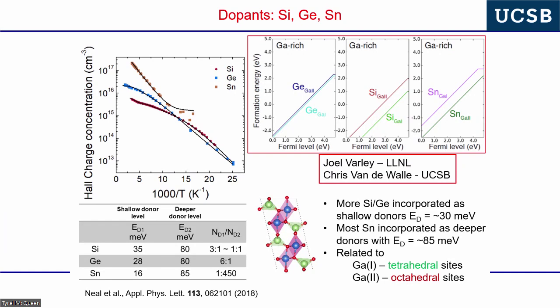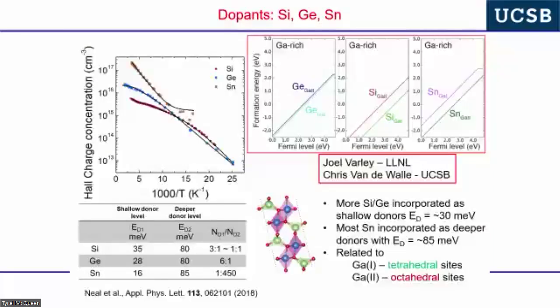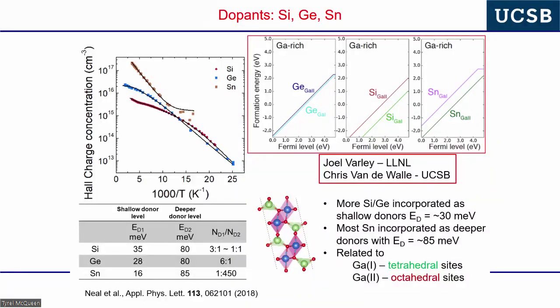Okay, and then we don't fit the slope of these in an Arrhenius plot. We actually take this data and we fit it to an equation called the charge neutrality equation. Okay, and from the charge neutrality equation, because we have way more data points than fitting parameters, typical fitting parameters are the donor ionization energies, the donor concentration, and the compensating acceptor concentration. So this comes out of semiconductor carrier statistics.